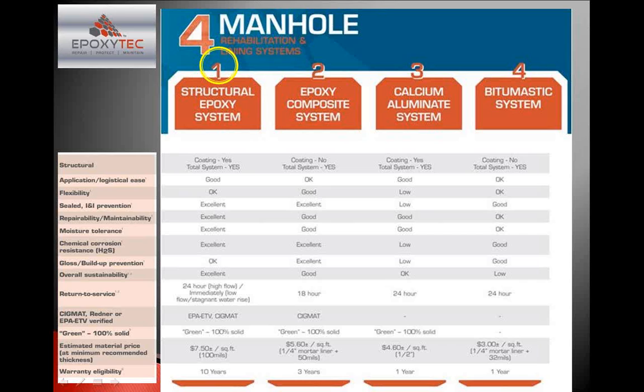Okay, so that was our structural epoxy system. Now let's look at our epoxy composite system. Our epoxy composite system would be, as I mentioned, a sewer-grade mortar that's top-coated by our urethane-modified epoxy. This has some flexibility to it because the urethane modification gives us about a 38% elongation. It is pretty good for I&I prevention. Okay, it has excellent chemical resistance. Well, no, epoxies are pretty good, and once you add a urethane modification to it, it becomes even better.